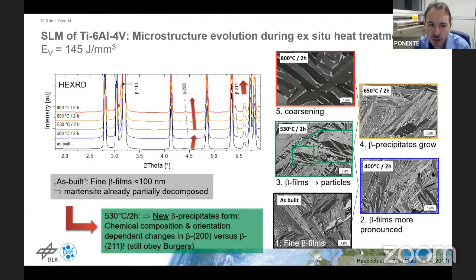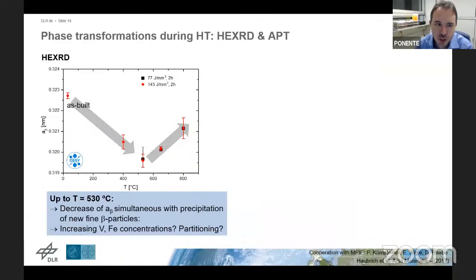And this we already get from SEM and XRD diffraction, and we wanted to understand the process further in order to optimize the microstructure. What we get from the XRD further is, if we calculate the lattice constant of the beta phase, a_beta, as a function of the heat treatment temperature, then we get this kind of diagram where you very clearly see, okay, here is a discontinuous change in the beta phase lattice parameter. There is a minimum at about 530 where we have these fine particles.